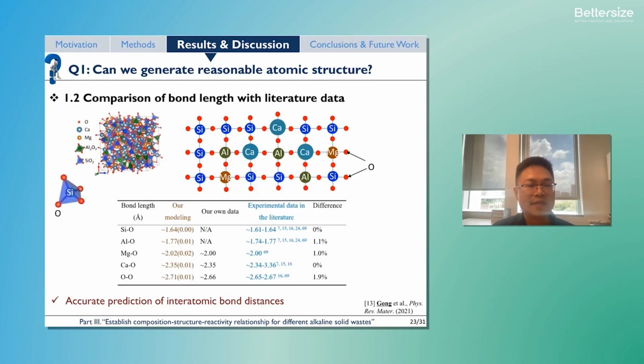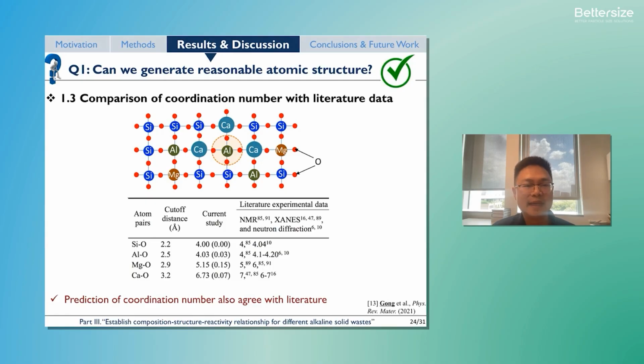I've also calculated the atomic bond distances within the materials based on the atomic structure and compared them with my own experimental data as well as literature data, as summarized in the table, which shows that the differences are smaller than 2%. Another comparison we did is the coordination number, which is defined as the number of oxygens in the nearest neighbor shell of a metal cation, as illustrated in the top figure. The comparison shows, as summarized in the bottom table, that they also agree reasonably well with the literature data on similar materials. Therefore, all these results show that reasonable atomic structures indeed can be generated using these atomic scale simulations.